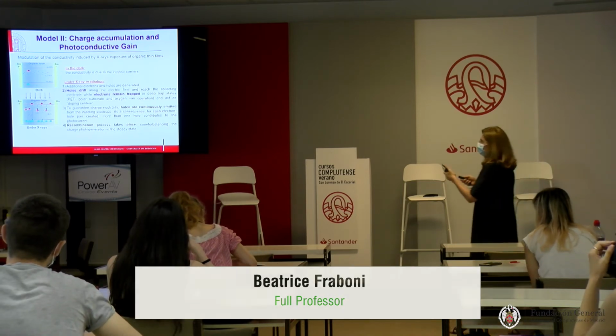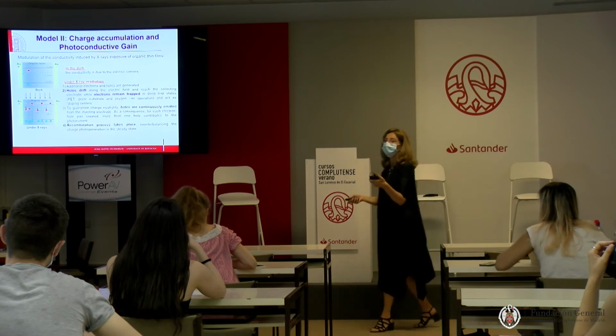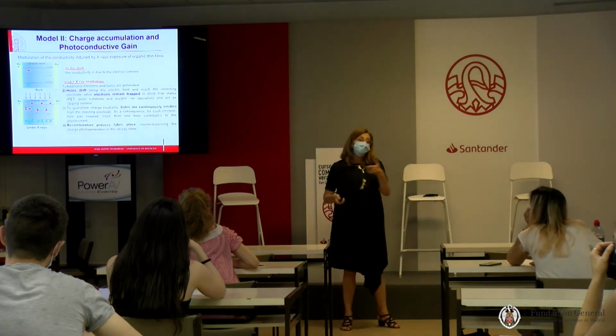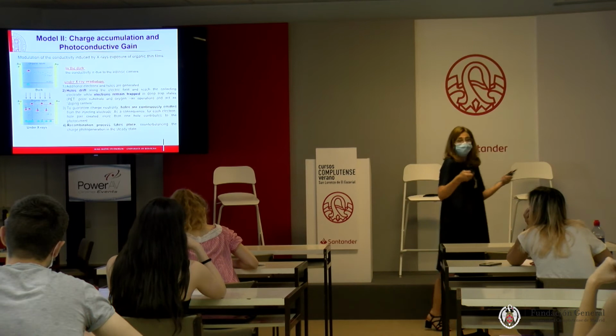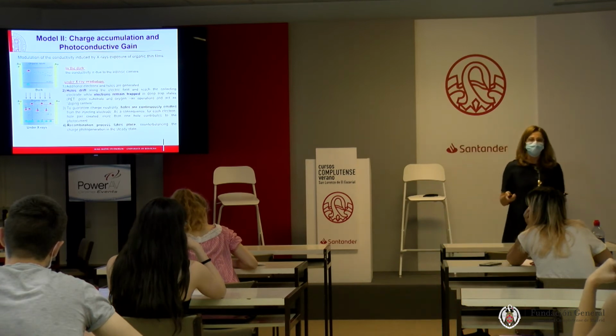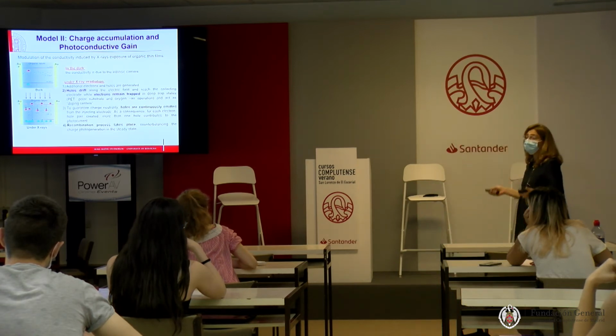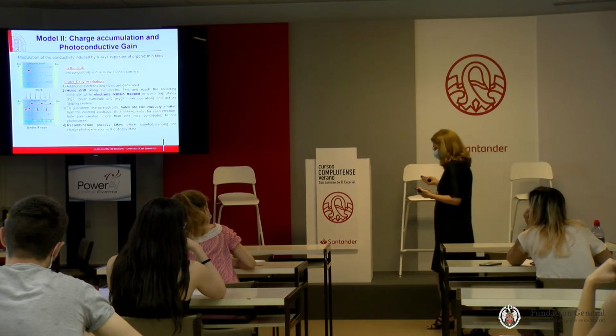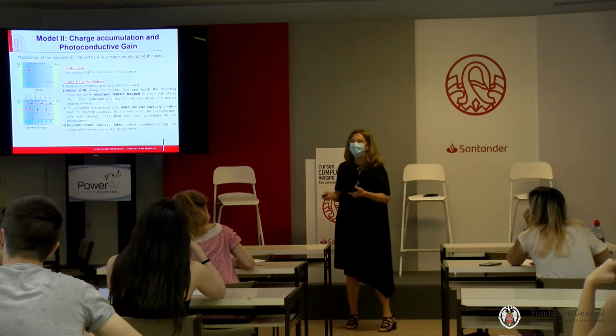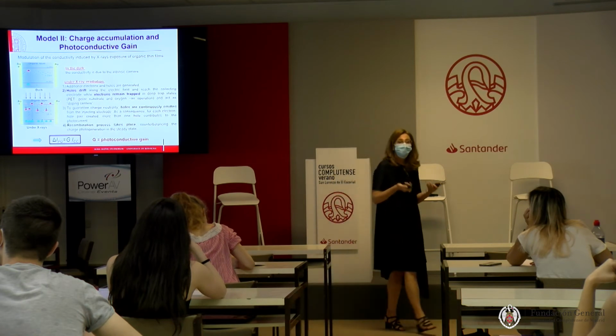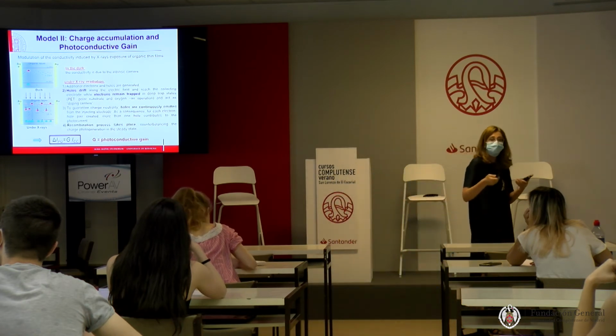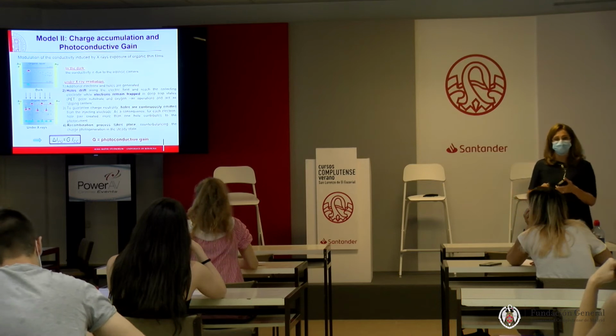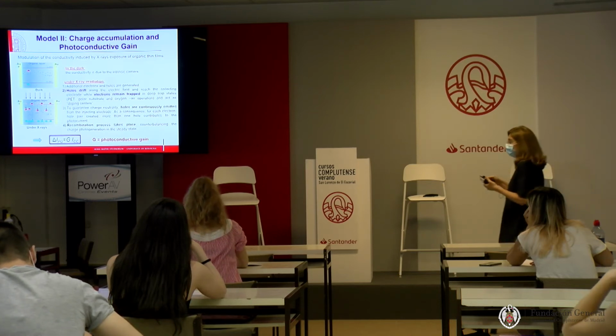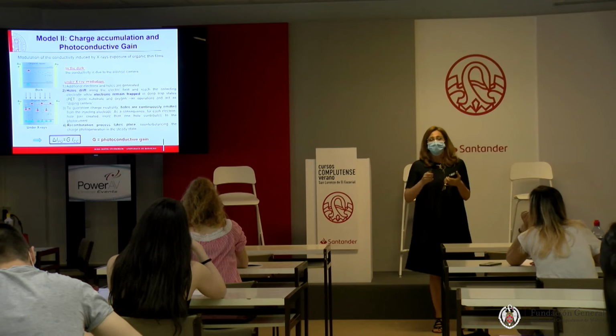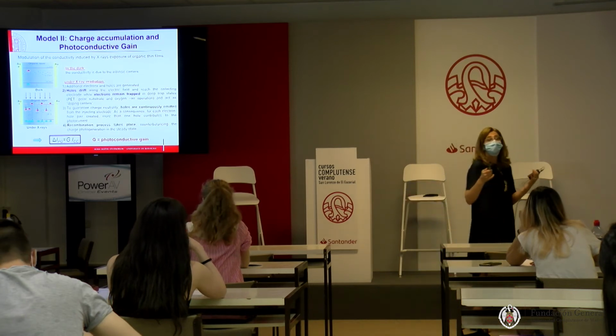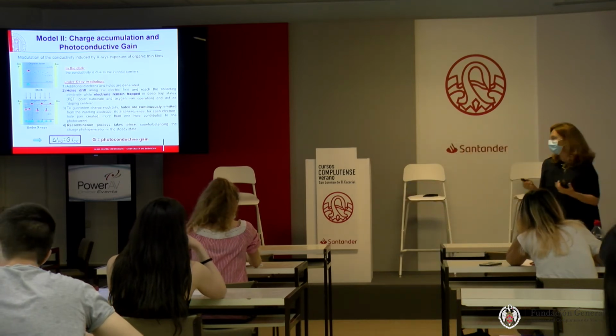So the X-ray generates holes, and the electrons stay trapped. To maintain the charge neutrality, more holes must be generated and collected. That is why we are collecting an extra current through a gain factor that is related to the trapping effect. This trapping effect ceases immediately once the irradiation stops and the traps re-emit the trapped electrons.